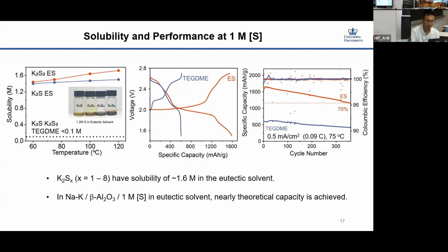Also here you can see that all the eutectic solvents have high solubility for almost all kinds of potassium polysulfides, potassium disulfide and potassium sulfide. So we first test a low loading of sulfur, which is equivalent to about 1 mole sulfur in the eutectic solvent. So in principle, it can fully dissolve in the electrolyte.